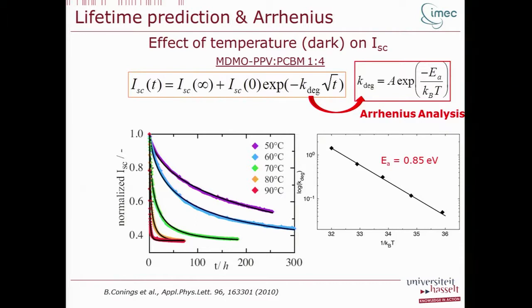And what do we think the relation to temperature could be? An Arrhenius relation, so this k is related to temperature through this activation energy. Well, if we fit these curves, we can do it very nicely with this formula, and you can retrieve very nicely an activation energy of 0.85 electron volt. So with this activation energy, you can really fit all these measurements between 50 and 90 degrees Celsius.